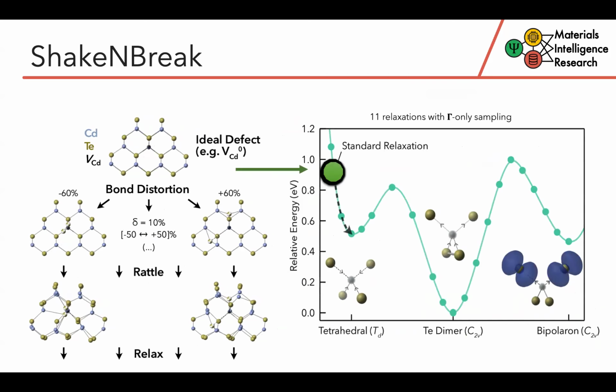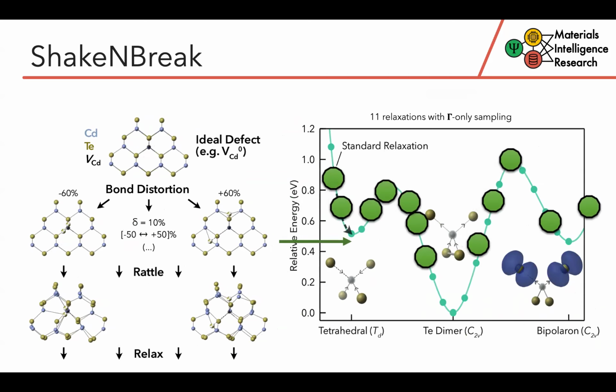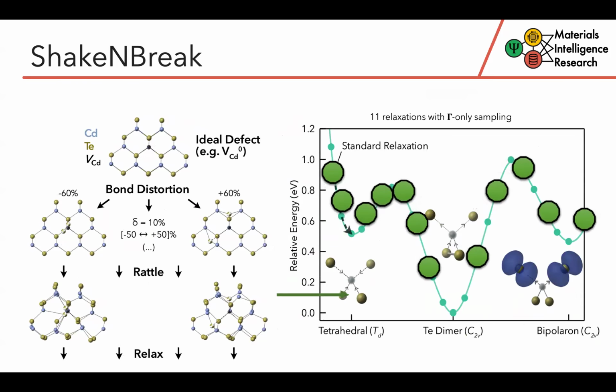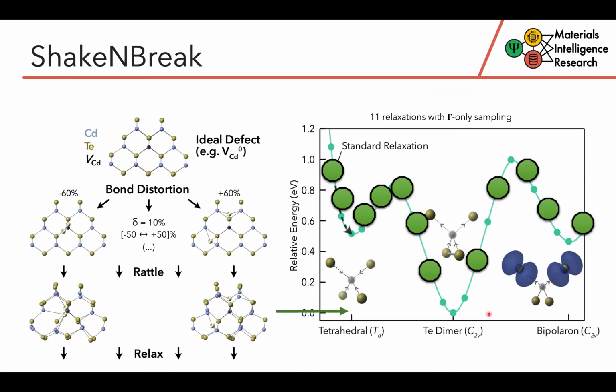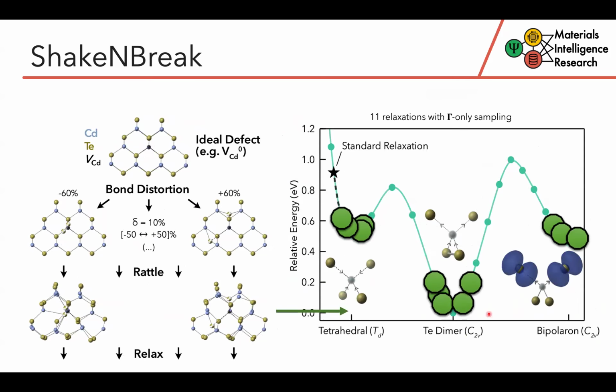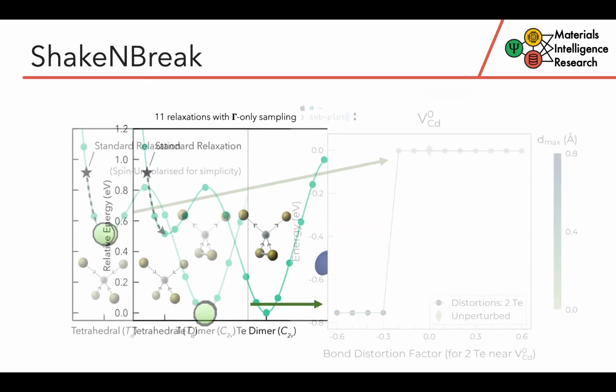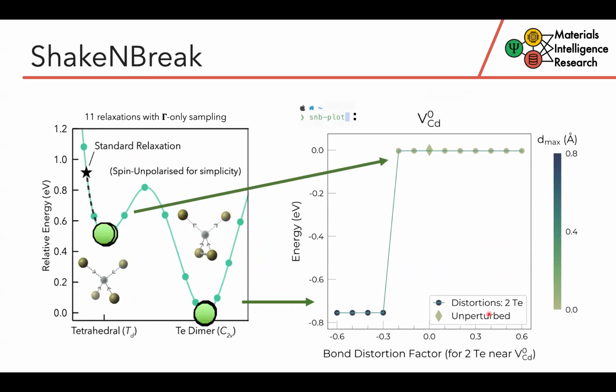So this gives us this kind of mesh of trial distortion structures, which we then relax using a reliable level of theory. So typically that's hybrid DFT when it comes to semiconductors, using cheap, coarse numerical parameters to help the calculations run efficiently. And then finally, we'll end up with something like this, where we can see that for a certain distortion range, our distortions have been sufficient to push us over this energy barrier and into the energy well of our ground state structure.